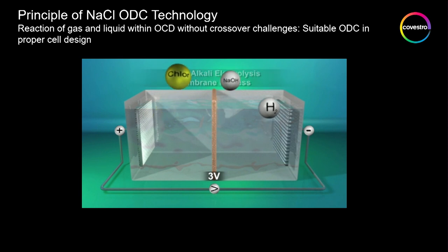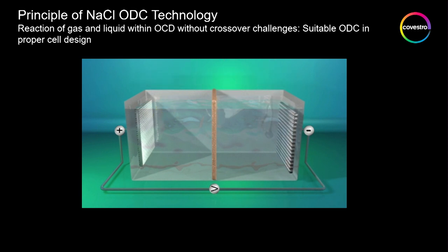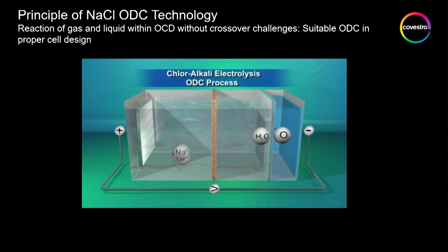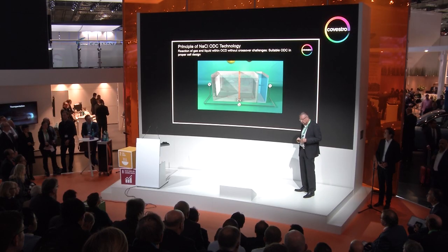Now, if you want to save energy, then you remove the hydrogen-forming cathode, put in an ODC electrode, and an additional raw material, which is oxygen. And by this, you get the same products, but without hydrogen. You keep it in your mind. It's a very important fact. But you can reduce the cell voltage by about 1 volt.